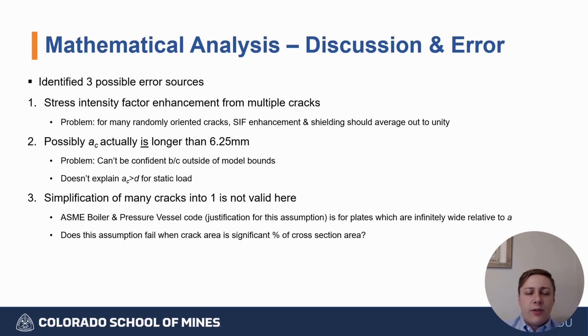So there are three possible sources of this error that we identified, and we'll discuss them briefly. One, it is possible that the interaction of many cracks in close proximity produced a stress intensity factor enhancement. However, we consider this a low probability explanation because for many randomly oriented cracks in close proximity, the combination of stress intensity factor enhancement and stress intensity factor reduction, depending on the orientation of the cracks, should cancel out to about unity.